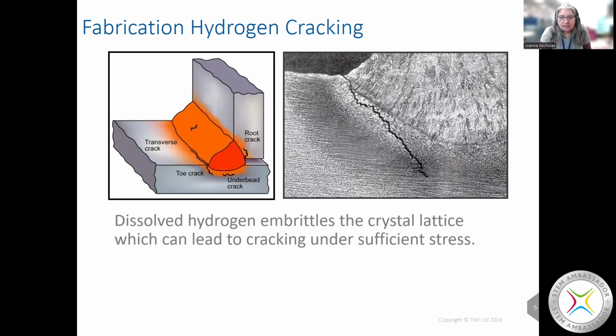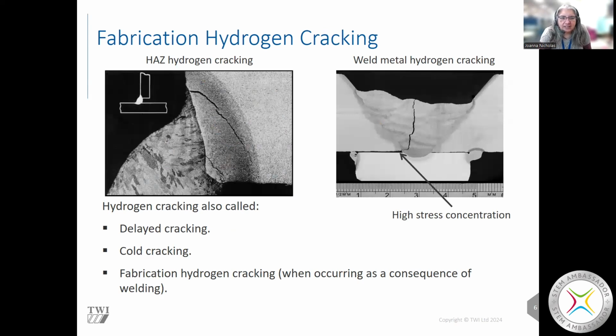Different locations where it can appear, and it appears a bit like this, pictures too, and it can be called lots of different names. Fabrication hydrogen cracking is the one that I would choose, but it could be called delayed cracking, cold cracking, because it happens when the material's fairly cold, down to about 150 degrees C. And it can happen in different locations, maybe in the HAZ, that's adjacent to the weld, the heat affected zone. So that's the parent steel that's not been melted, but it's been changed a bit because of the heat of welding, or in the weld metal itself.